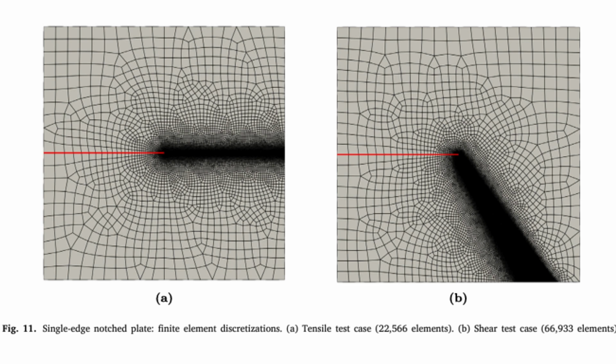That does sound elegant, but you mentioned earlier this leads to non-convex energy functionals. That's the downside. That's the core difficulty, yes. Non-convex means the energy landscape isn't a simple bowl shape where you just roll downhill to the lowest point, the solution. It has lots of local minima, bumps and valleys. Like trying to find the lowest point in a mountain range instead of a smooth valley. Good analogy. And standard solvers, monolithic ones like Newton-Raphson, can easily get stuck in a local valley, or worse, when the crack starts growing rapidly and the landscape changes violently, they just lose their footing completely. They diverge. That's the brutal crack evolution problem again.